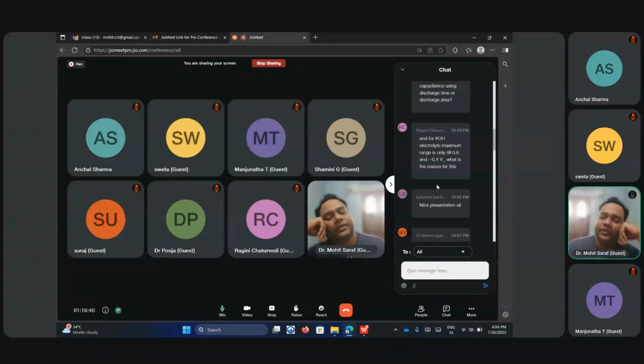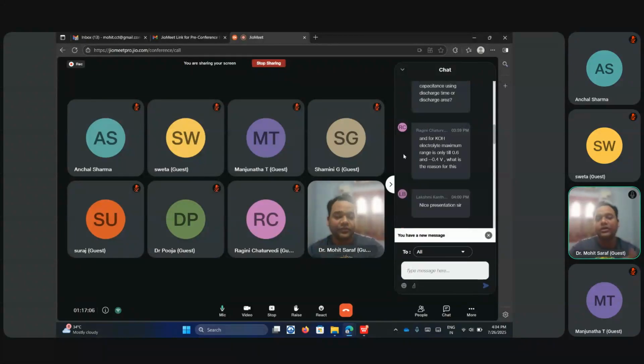Yeah, as I mentioned, the electrolyte changes the electrochemistry. It is about the mobility of your ions. Let's say you have sulfuric acid. The mobility of the proton, the H ion, is very high, so you might trigger the oxidation and reduction very quickly. On the other hand, if you have OH ions or any other ions, it depends on how quickly your ions can move in the electrolyte. If it is fast, then maybe you are triggering your oxidation and other events very quickly, and then you are limiting the voltage somehow. So it depends on the mobility of your ions.